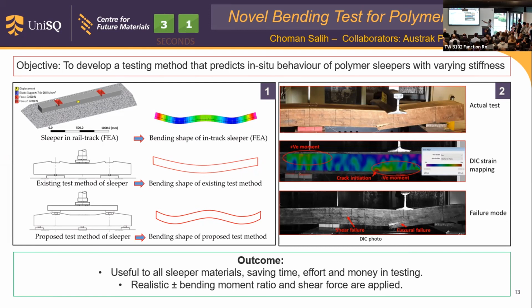However, the current testing standard doesn't consider this bending shape and requires many tests to achieve that. Therefore, I'm presenting a 5-point bending test where you can see a W shape is obtained. And the second photo shows the actual photo of the test where you see a timber sleeper failed, with DIC strain mapping and the failure mode shown in the bottom.